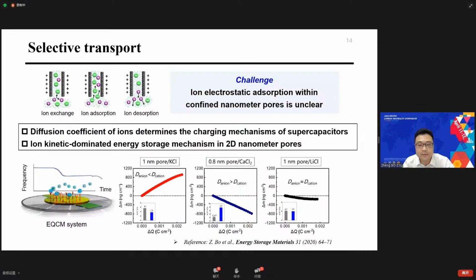During the electrostatic process, ion mass transfer can be divided into three forms: ion exchange, ion adsorption, and ion desorption. For the planar electrode or pore size that is large enough, ion exchange is the major form. But for ion electrostatic adsorption confined in nanometer pores, it is still unclear, and I use EQCM to get some measurements and try to find out the major.